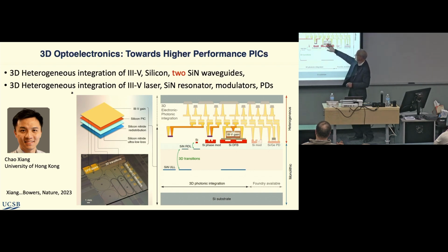We have silicon waveguides with III-V gain. We couple these silicon waveguides to silicon nitride waveguides, and this is sort of a redistribution layer. Then there's another layer that's down here that we couple from here down to here. So there's a lot of transitions. They're all adiabatic tapered transitions. So the design of that is important, and having fine fingertips is important.